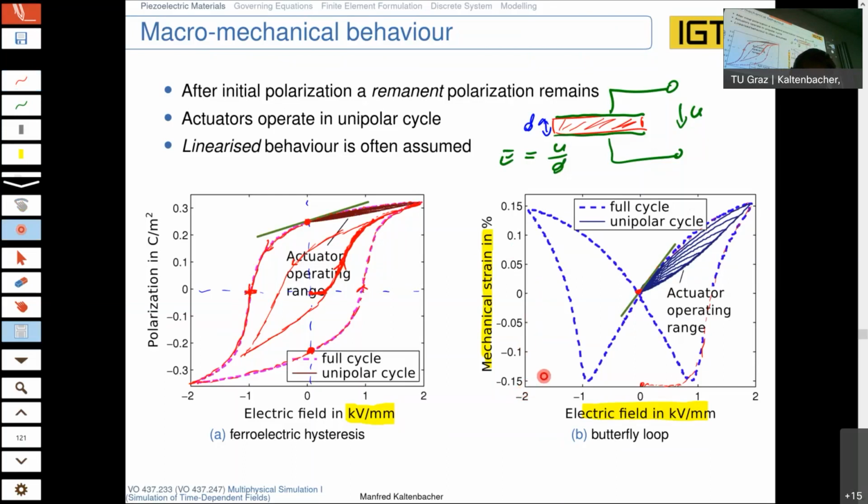This is an offset, so actually it would be here 0.15% we would have. So you have to shift this up, and this is, as shown here, the wrong zero line. Yeah, but that is what you really get out. That was the intention, to show you. When you do measurements, it will look in this case like this one.